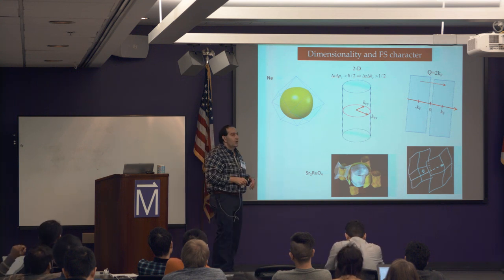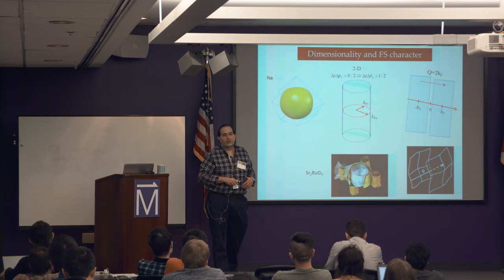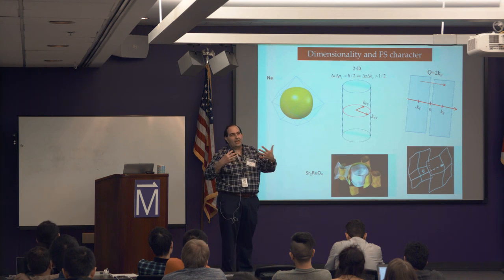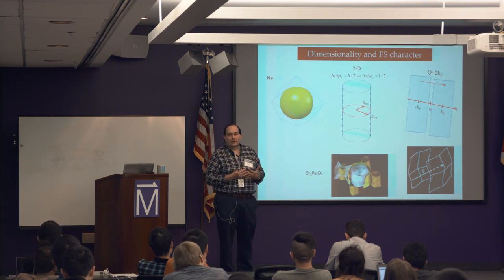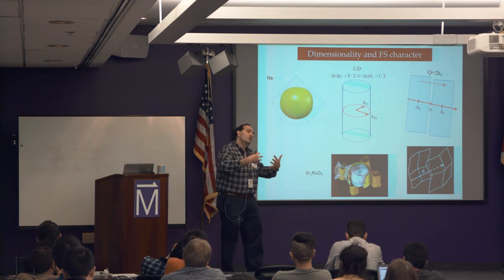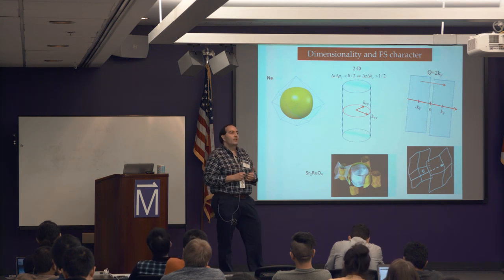And it's important to know the geometry of Fermi surfaces. The cuprates, the ruthenates, and many oxides have two-dimensional Fermi surfaces. And the geometry of the Fermi surface is going to define separate parameters, like the symmetry of the superconducting gap if it's a superconductor, okay? So by just knowing the geometry of the Fermi surface, you can infer a lot of properties of the material